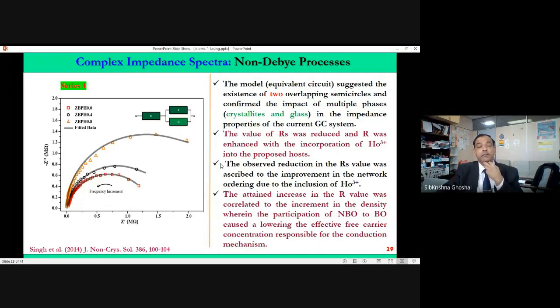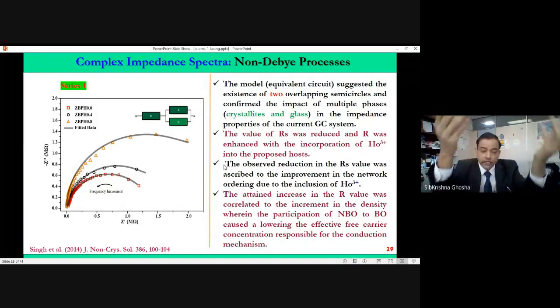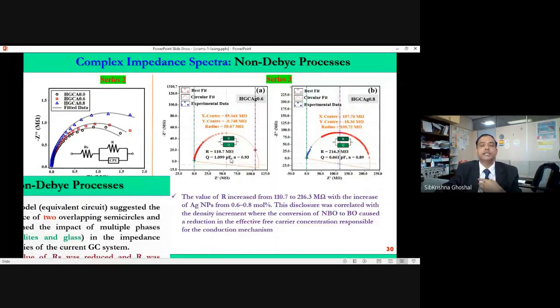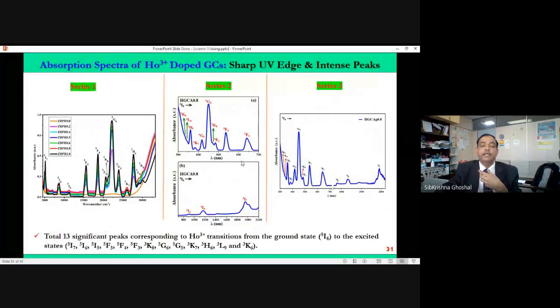Then we look at the impedance, resistance, and also the dielectric constant, complex dielectric constant, because complex dielectric constant is related to the refractive index of the material. So refractive index we measure, refractive index we calculate from the Lorentz-Lorenz formula, the Dimitrov-Sakka relationship. Then we also calculate the refractive index from the dielectric constant, from the dielectric measurement. We want to match, we want to cross-relate, and then compare with the experiment. So from all such data, we see that they are really correlated.